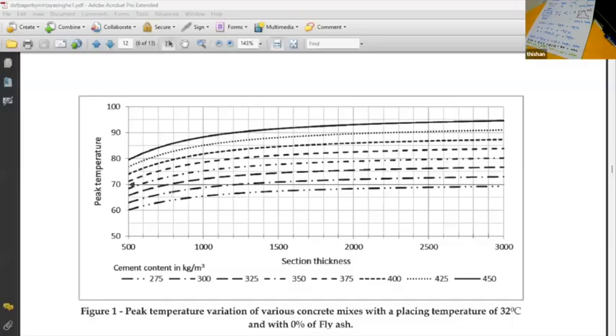Because if you look at the chart, you can see when the thickness is 300 millimeters, even if you are using 350, this 275, 300, 350, 375. Even when you are using 375 cement, still the temperature is less than 70, so you have no problem. So don't use fly ash. In that case, use cement and do the concrete. So you get very high strength gain over a very short period, and you can remove the formwork.